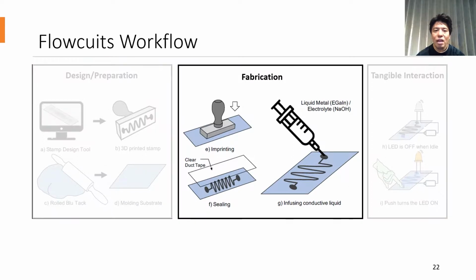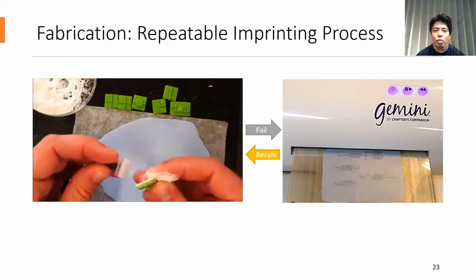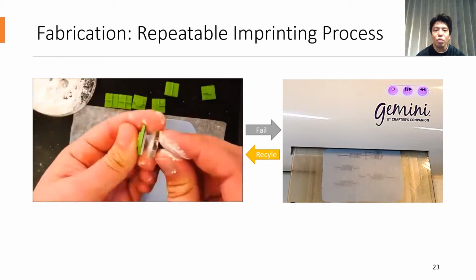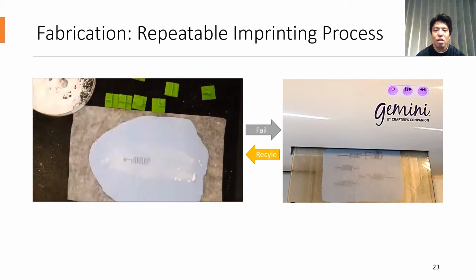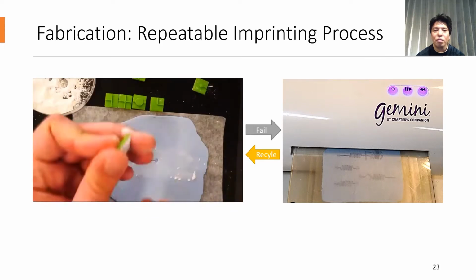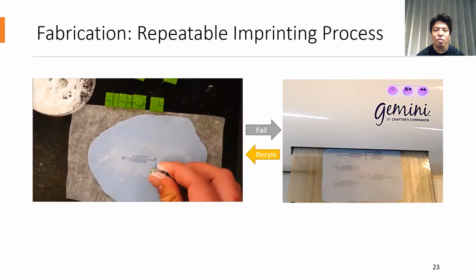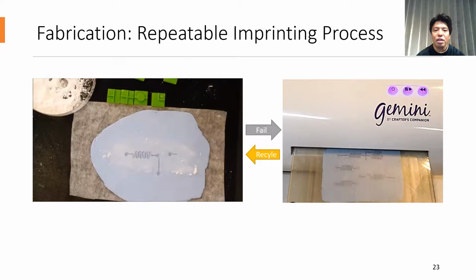Next, I will move on to the fabrication step. Since Blu-Tack is very adhesive to the 3D printed stamp, we must coat the surface with fine powder, such as cornstarch, before imprinting. We can restore the Blu-Tack adhesiveness by cleaning the surface with water. If imprinting fails, we can recycle Blu-Tack through a clay roller machine.